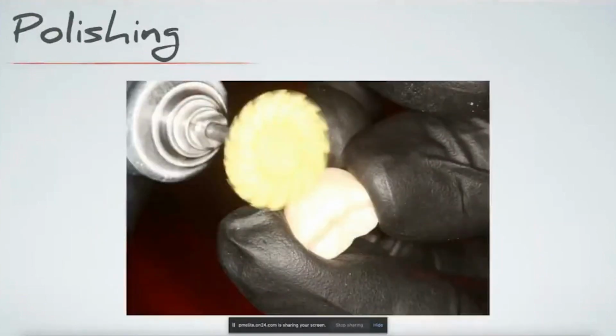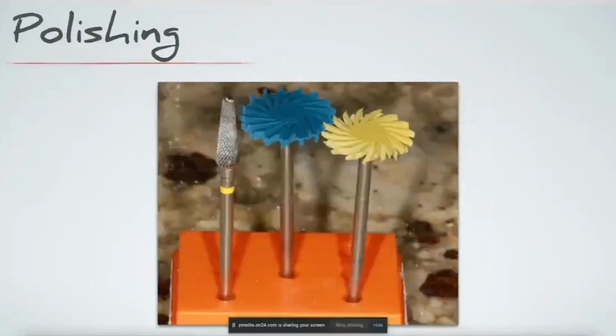Then we're going to do some post-sintering polishing. Same system, this yellow wheel from Meisinger is the last one for a high shine. And I would recommend not doing this too much. We like to get a nice shine. Zirconia polishes beautifully. So easy to polish, but it's easy to over-polish it. And when you over-polish it, it's almost going to become this pearl opalescence type color. I don't love that as much. Patients sometimes almost say the crowns feel too slick, right? But a simple light touch with this yellow polishing wheel from Meisinger into the occlusal anatomy around the margins, and you'll be in good shape.